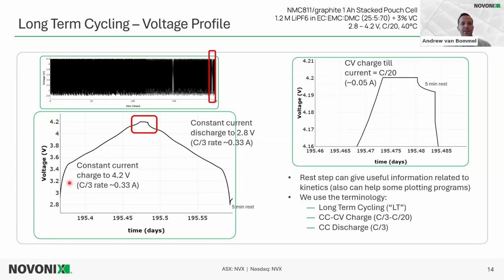For this 811 cell, this is charged to 4.2 volts. After that, there is a CV step, which is a constant voltage charge step. This ensures that there's still capacity from the charge step, but we don't go over the 4.2 volts, which is important for something like NMC 811 when trying to get good lifetime from those cells. So we have that CV step until C/20 current, which is 50 milliamps for this cell. And then afterwards, we have a 5-minute rest step. So we use this following terminology here for our customers. We call this long-term or LT, long-term cycling.